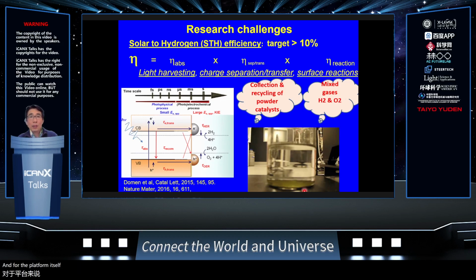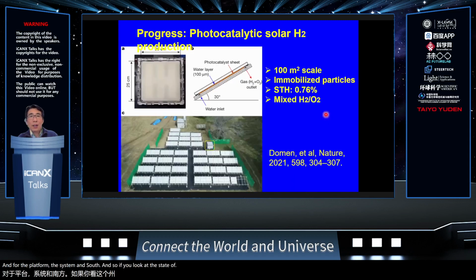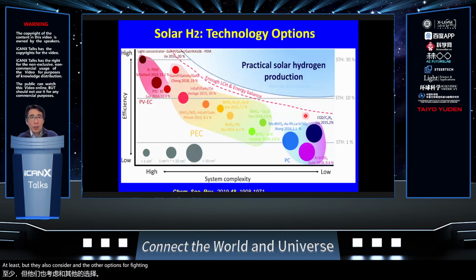And for the powder form system, if you look at the state of the art technology, that's basically led by Professor Domen at Tokyo University, and they can produce a very large scale photocatalytic sheet, but the efficiency so far is less than 1%. So that's already the world best, and we still have a long way to go if we really want to achieve 10% efficiency. We are also doing some powder-based photocatalyst, but we also consider other options for hydrogen production. Certainly, if we really want to push the cost to be very low, we go in this direction, that's photocatalyst, but the efficiency is very low.